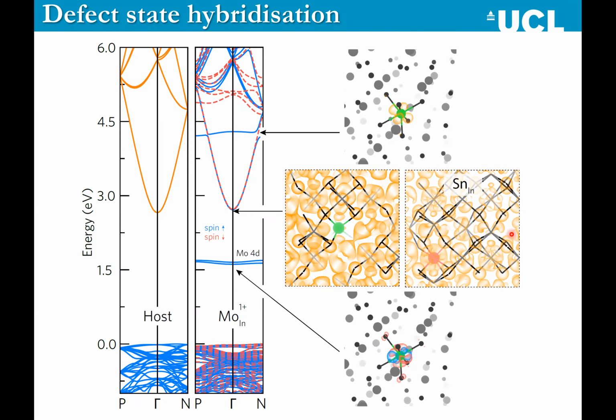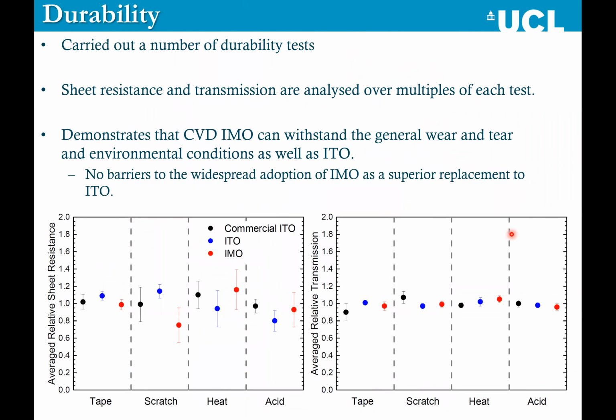So of course, my dean was very interested in seeing, could we basically get some interest from industry? So what we did was we carried out a number of durability tests on the doped indium oxides, and we showed that basically CVD grown IMO has basically the exact same performance as ITO in terms of its ability to weather general wear and tear. So there should be no barriers to the widespread adoption of IMO as a replacement to ITO.